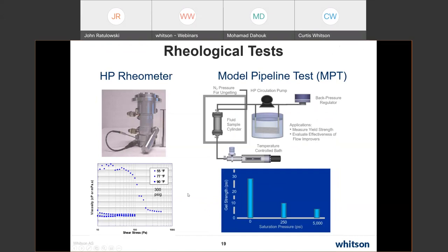So for rheometry, you can use a high pressure rheometer to measure live oil, shear dependent rheometry. And you can see here, as we reduce temperature, at high temperatures it's very Newtonian, with a low viscosity. Then you drop well below the wax appearance temperature at this 55 degrees Fahrenheit, and I get a much higher viscosity and a large shear dependency. So as we go down to zero shear, this thing is trying to gel up.